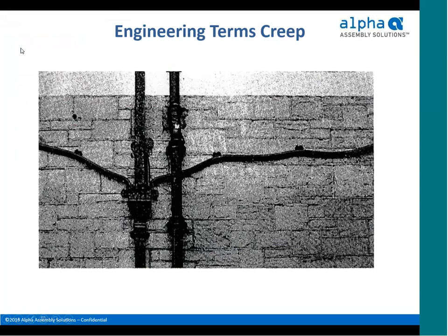Here's an example of creep. What you see here are some very old, and I'm talking about centuries old, lead pipes. The pipes running off to the left and to the right, between each of those brackets that attached them to the wall, ran straight when they were installed. But because of the weight of the water inside of the pipe over the course of the life of the pipe, it applied creep stress, which caused those pipes to sag. And the same phenomenon can occur to solder when you're connected to a solder joint.